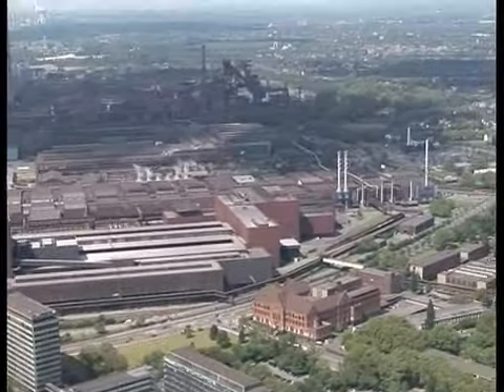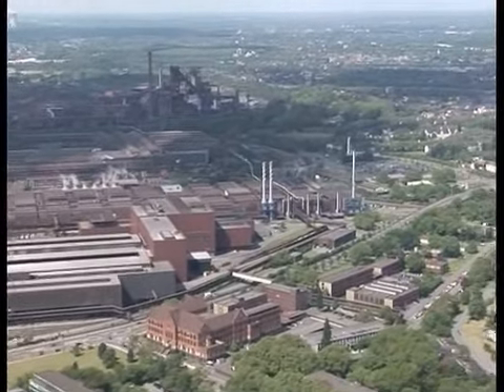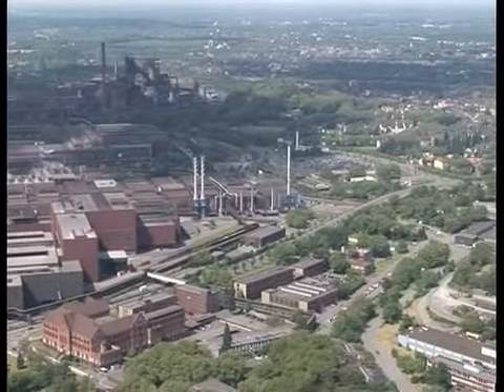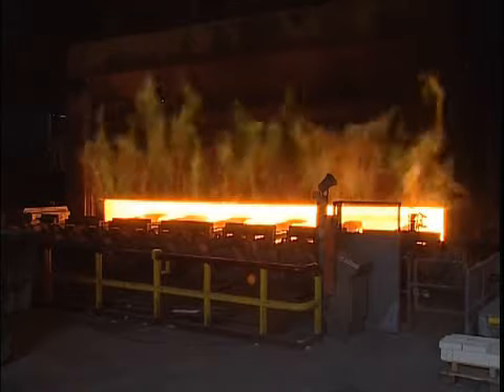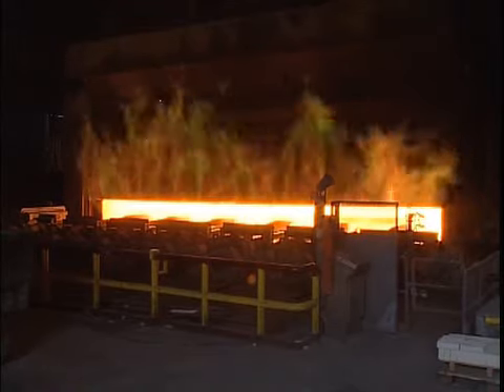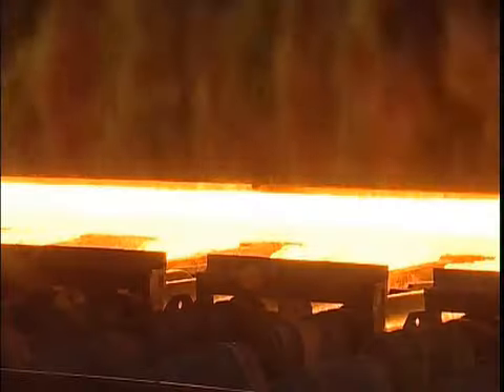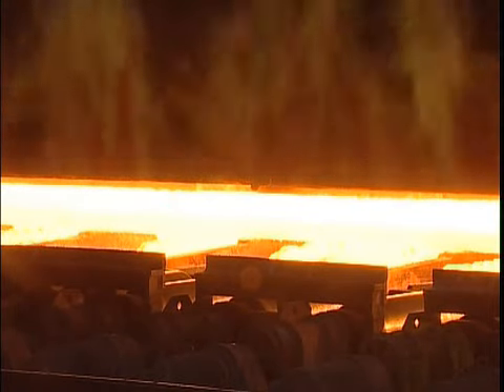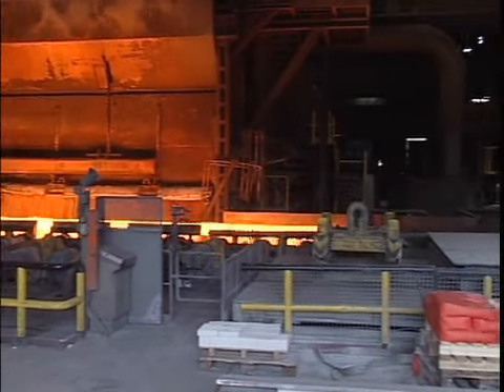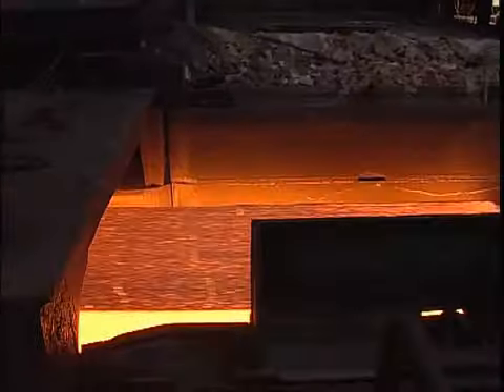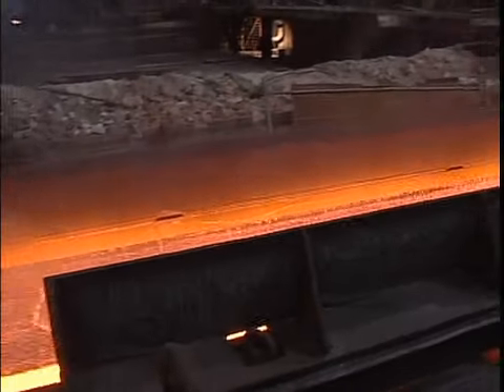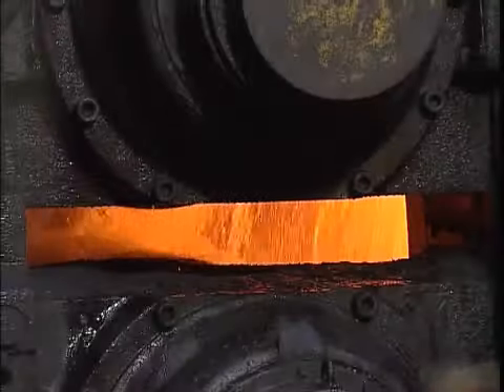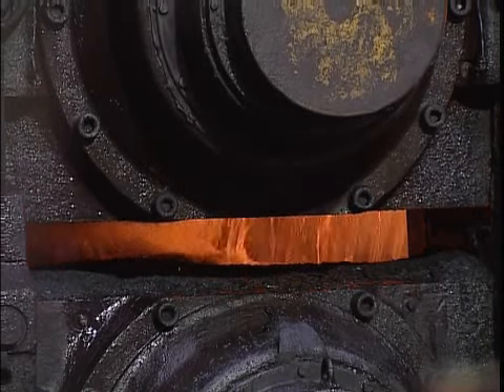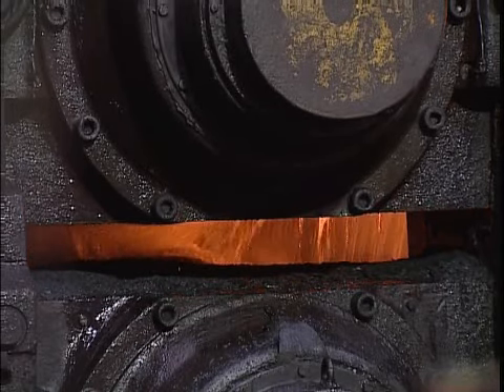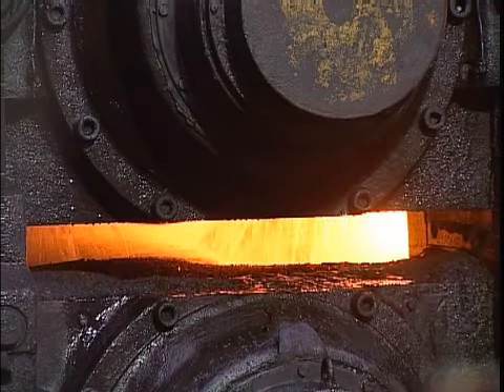In the Bruckhausen hot rolling plant of ThyssenKrupp Stahl AG in Duisburg, the hot slabs are reheated in a walking beam furnace up to a temperature just below the melting point. White hot slabs leave the furnace and are hot rolled directly, according to a reduction schedule adjusted to the respective alloy. A reversing roughing mill reduces the slabs 216 millimeters in thickness into a transfer bar.